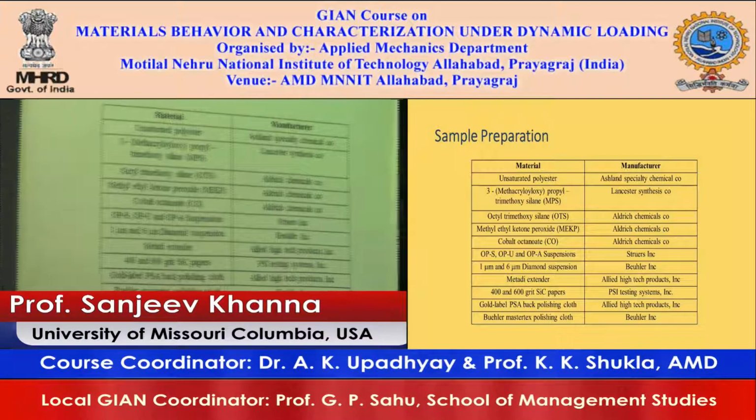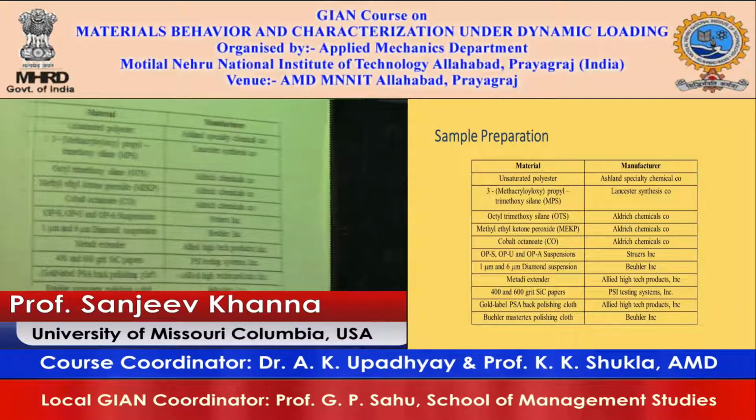Now OPS and OPU, these are two suspensions which have colloidal silica particles in them. Those silica particles are 40 nanometers in diameter, okay, or in basic size.